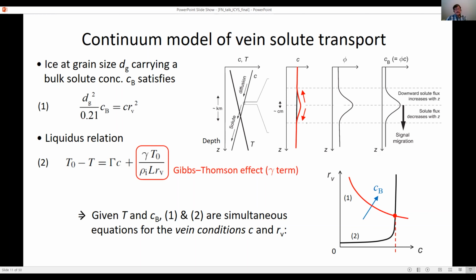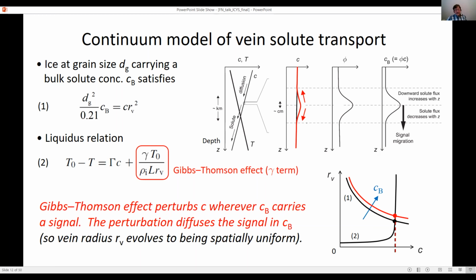But what happens now is that this second equation is no longer a straight line. If you're interested in mathematics, this is basically a solution telling us conditions in veins at a certain place. But now, because equation 2 isn't a vertical line, it's tilted. When you get a signal in the bulk concentration, you move across it, there's a little perturbation on the vein impurity concentration that causes diffusion. Yes, again, it's very shallow, but that actually diffuses the main signal. So that's summarized here. There is this Gibbs-Thomson effect, which perturbs the local vein chemical concentration, which in turn diffuses the bulk signal.